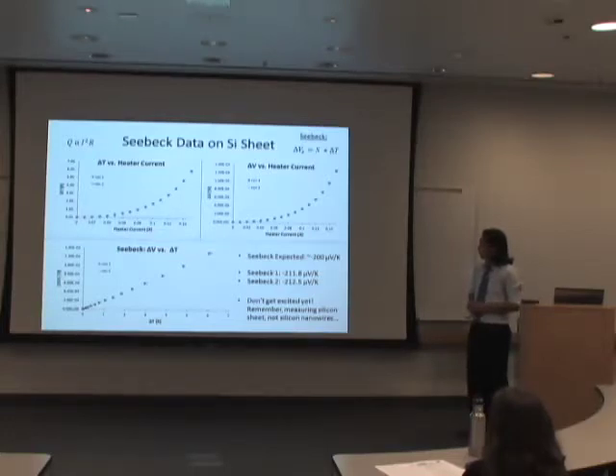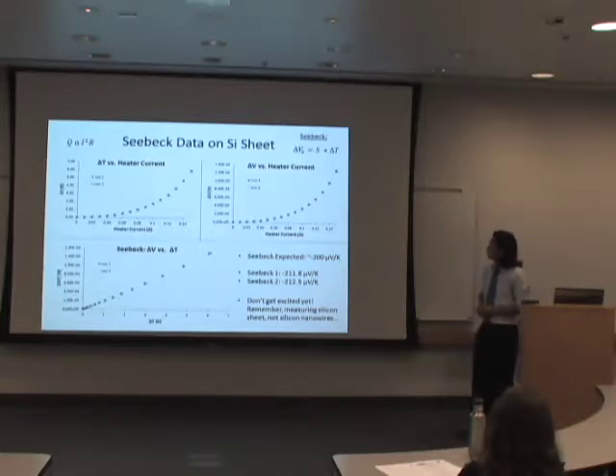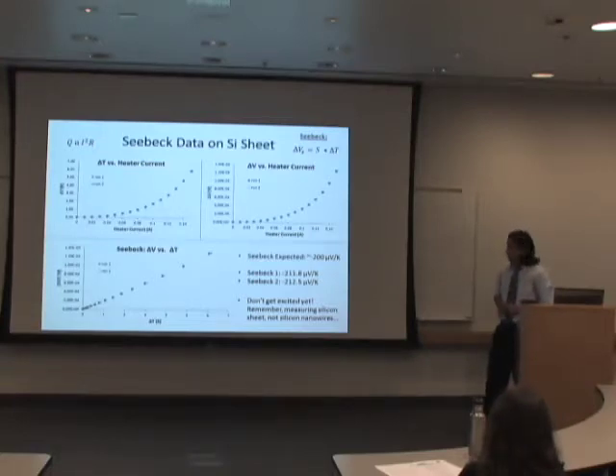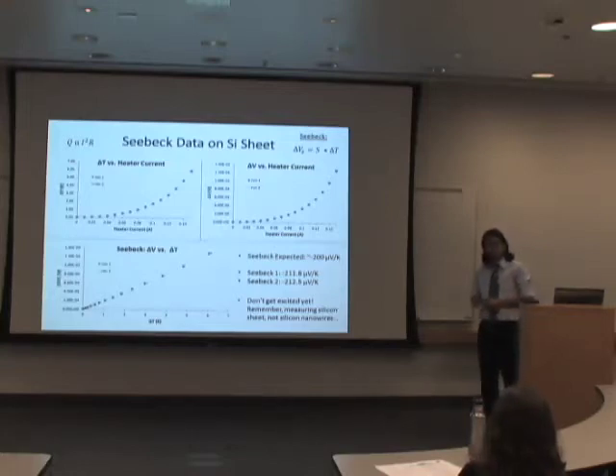Here we have the measured voltage versus heater current. It's a function of the current to the heater. Again, it follows the same trend as the previous one, as it should in this equation. And finally, we plot the Seebeck coefficient, which is what we're interested in. And again, it's a linear relationship as it should be. We expected about negative 200 microvolts per Kelvin. We obtained about 211.8 and 212.5, which is very precise, as you can tell. However, this measurement was done on a silicon sheet and not actually the silicon nanowires, because we're first testing the routine to make sure it works on a silicon sheet, which is much easier to measure than the nanowires.